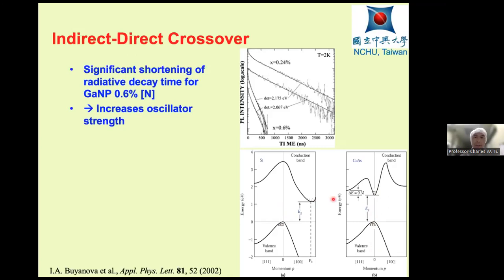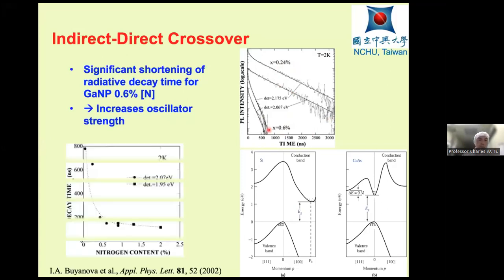What she found is that she looked at the photoluminescence as a function of time. You apply a light, then you create electron hole pairs, and then they recombine. Then you observe photoluminescence, and as a function of time, you see how this light decreases. What you find is that for 0.24% nitrogen, the lifetime is long. But when it's 0.6% nitrogen, the lifetime is short. So if you plot lifetime as a function of nitrogen content, you find that at about 0.4% or 0.5%, there are two groups, the long lifetime and the short lifetime.